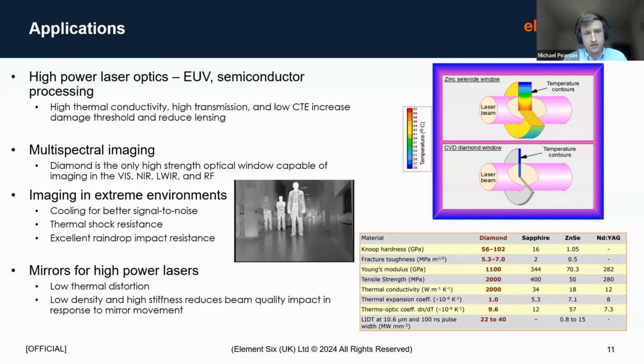Now, the drive laser that generates that CO2 laser to hit your tin droplet has a number of diamond windows in it, and the reason we're using diamond in that application is for the thermal management and the high transmission at 10.6. So we've talked a bit about zinc selenide. It's really that application where the coating absorption can only be managed using a diamond window. Alternative materials just won't cope in that very extreme environment.